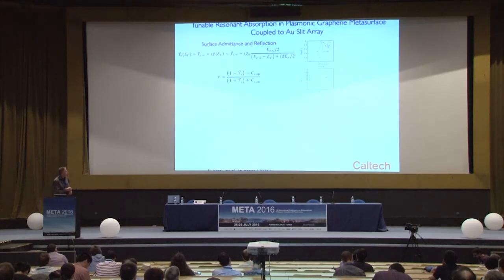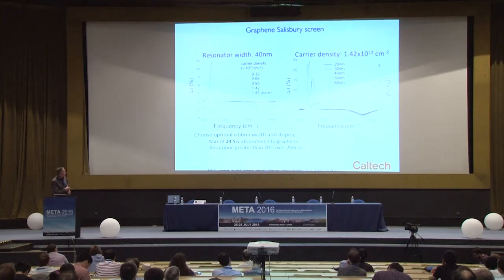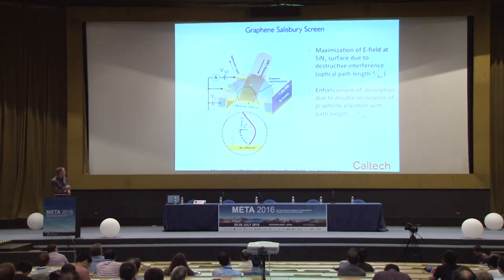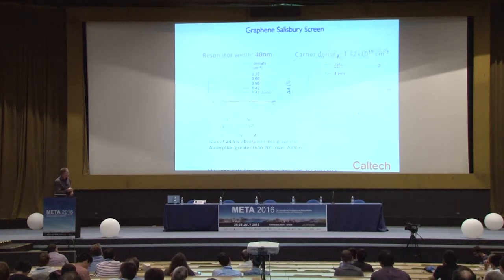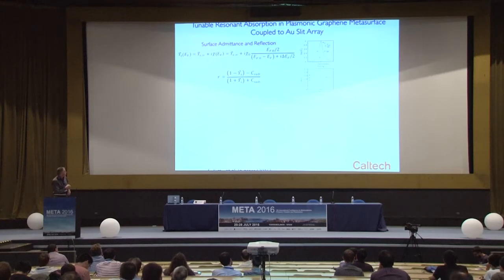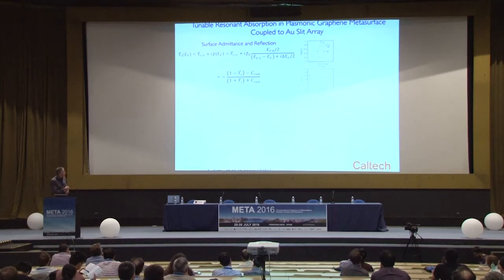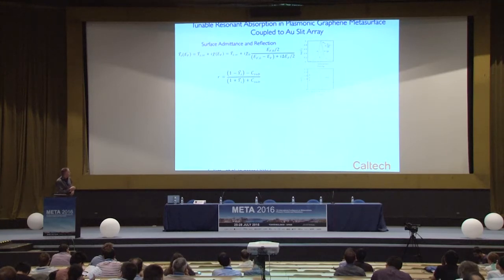And we can, of course, view the resonators as having a real and complex part of their susceptibility or admittance. And essentially what we can do, because the whole structure is deeply sub-wavelength in dimensions, here the mid-infrared wavelength is 7 microns, and the whole structure here is about a micron thick, so then we can essentially form an effective surface admittance that contains a component that's characteristic of a highly conducting surface and a tunable component. And then in order to obtain a zero reflectivity condition, we're going to essentially zero the numerator, which is this 1 minus admittance, and a factor, this coupling factor, which is proportional to the properties of the substrate.